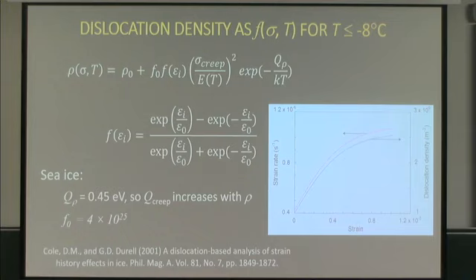There was no real basis for getting this relationship theoretically. So Glenn Durrell, my colleague, went down cellar and came back in about a year with a huge amount of data at a variety of stresses and temperatures on sea ice. All this original work is done on sea ice. And we were able to come up with this second power stress relationship for the dislocation density. So that's our key parameter that's going to drive the behavior, the constitutive behavior that we're looking at.